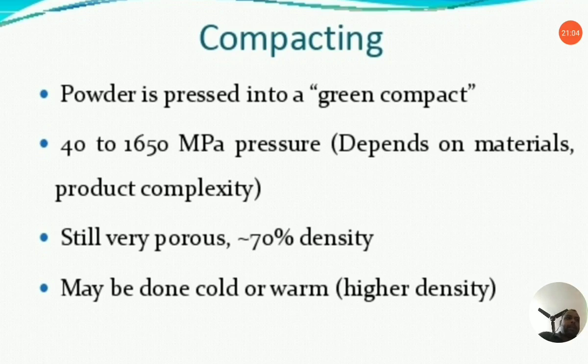compact, which is a very important step in powder metallurgy. The desired characteristics to be achieved by compacting are high product density and uniformity of that density throughout the compact. Okay. Now, compacting is generally accomplished by the use of mechanical presses and rigid tools, but hydraulic presses are also being used. Compaction pressures generally, as you can see, range from 40 to 1650 MPa. Maximum capacity for the powder metallurgy press may be of the order of 1 mega Newton or less.